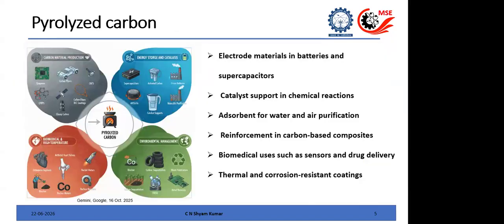So pyrolyzed carbon is now in different technological applications. It's widely used in a variety of applications like electrode materials in batteries and supercapacitors. The lithium-ion battery uses graphite. But when it comes to post-lithium-ion batteries like sodium or potassium, the graphitic layers cannot host the bigger potassium and sodium ions. So there you need a material which does not ideally have the exact graphitic layer thickness, which is 3.34 angstrom. You need a bit of disorder, so that the layers are not perfectly graphitic, and you have more space between the layers, so that the bigger atoms can go.